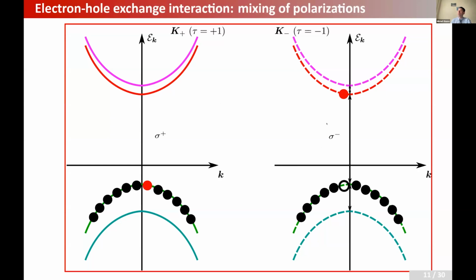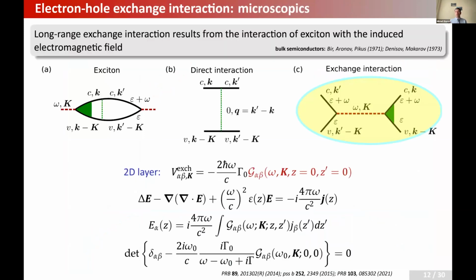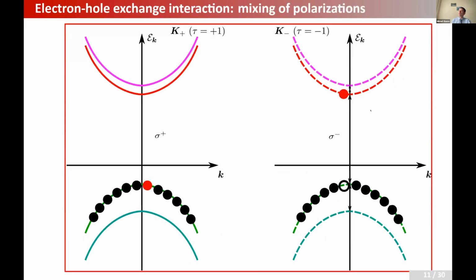Now this electron-hole pair will emit sigma minus polarized light. So this is just a cartoon example of how the long-range exchange interaction works in excitons. Of course, you can do a more sophisticated theory. Actually, you can deal with this problem in many different ways. Back in the days, this problem was attacked from several directions. You can, for instance, just calculate the Coulomb interaction exactly as I explained here, the interaction between these and these guys, and calculate the corresponding matrix elements.